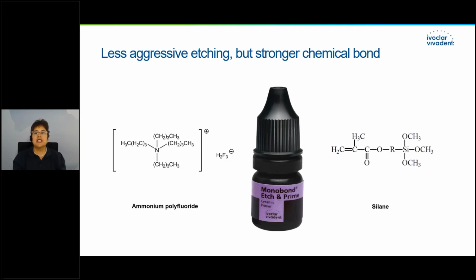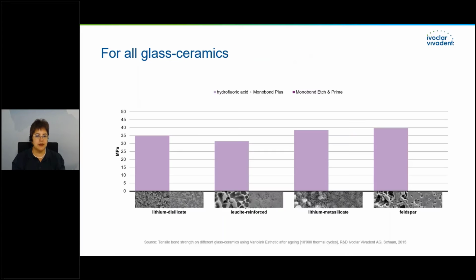So Monobond Etch and Prime has a less aggressive etching than hydrofluoric acid. Despite containing HF ions in this formulation, it is not releasing hydrofluoric acid in water solution. This is ammonium polyfluoride. And it is less toxic than hydrofluoric acid, and additionally, it contains as a second component silane.